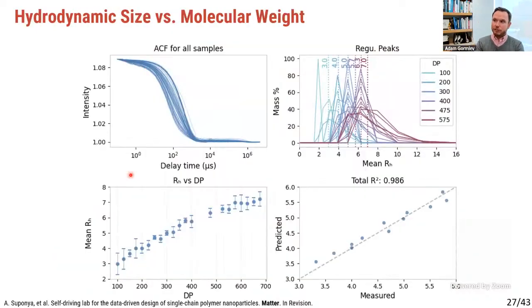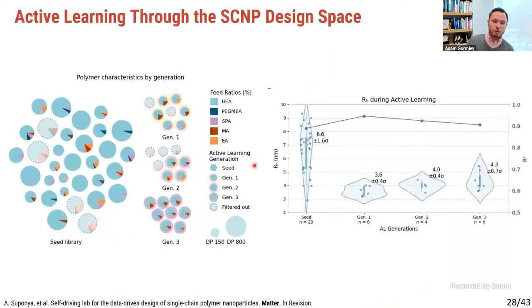We did a lot of validation of these experiments. What's really important is that the validations worked very well. The data quality that was coming out after a lot of work was excellent. If you look here on the bottom left-hand corner, this is hydrodynamic radius. So how big is the macromolecule versus molecular weight of the macromolecule. The bigger the molecular weight, the bigger the hydrodynamic radius. And we see that really beautifully, meaning that the data quality is very high from our system after we did a lot of work trying to figure out how to manage the data. I can tell you that a lot of work went into this, and we get very high predictive accuracies. And so this was a fully autonomous self-driving experiment.